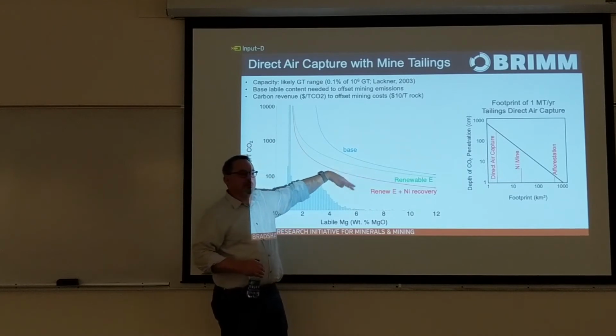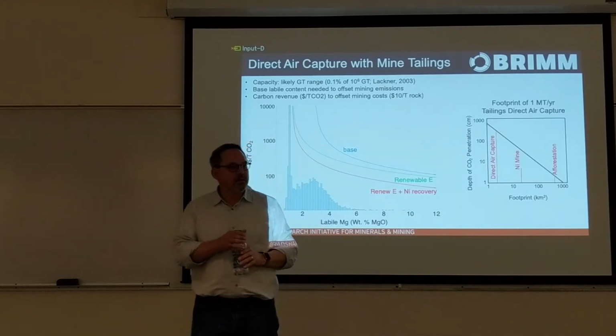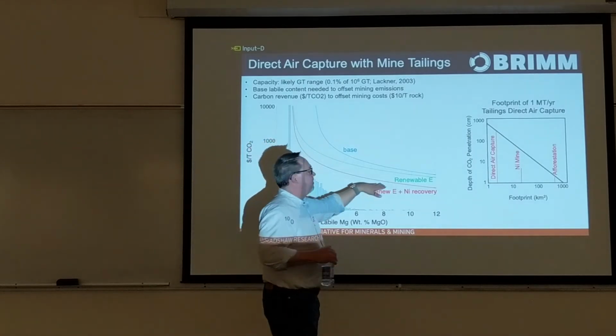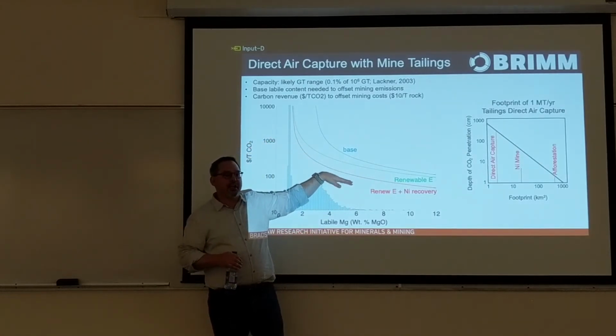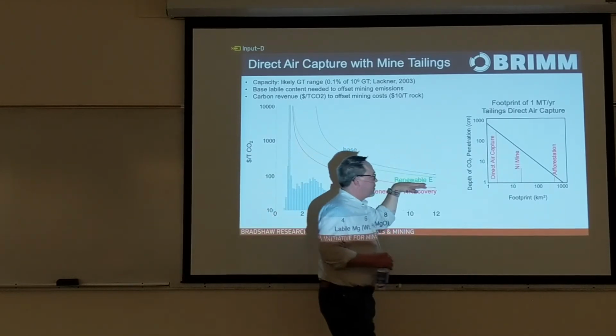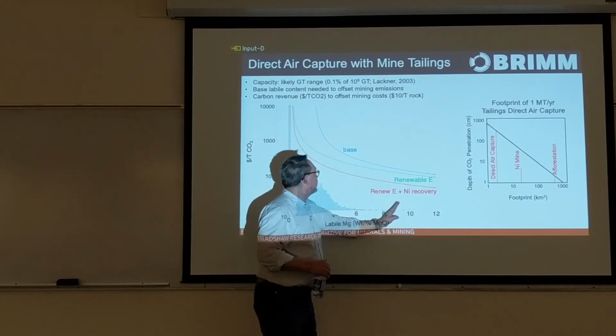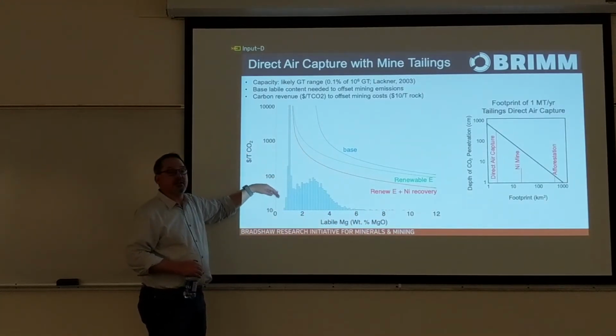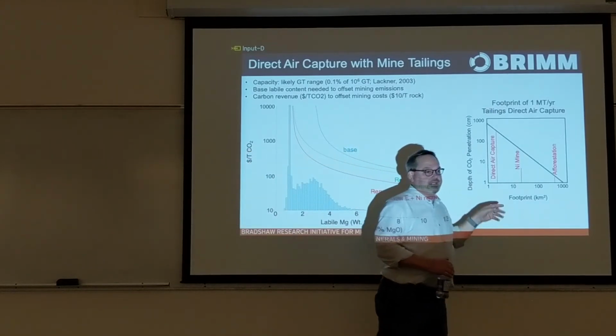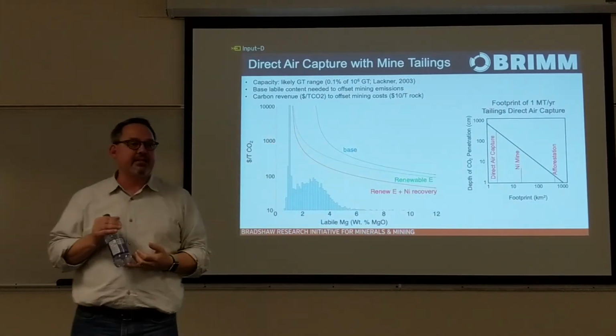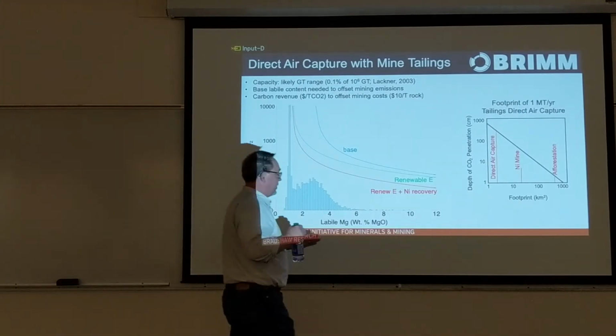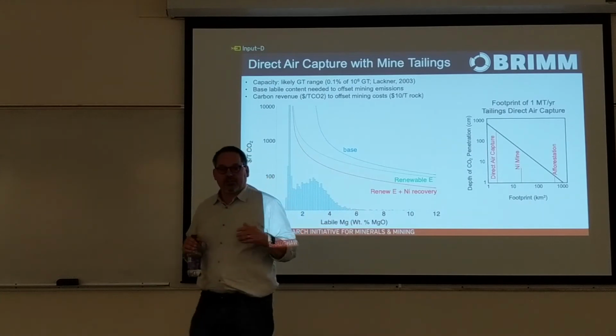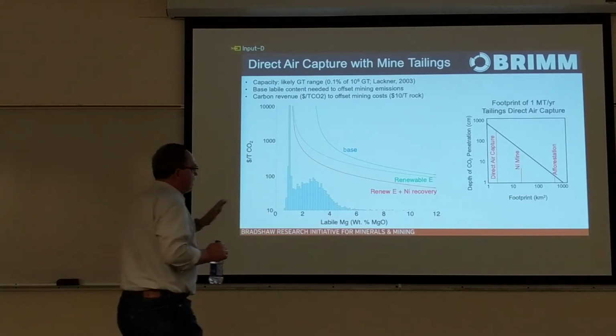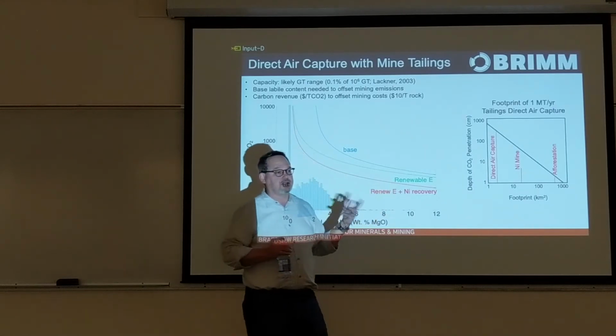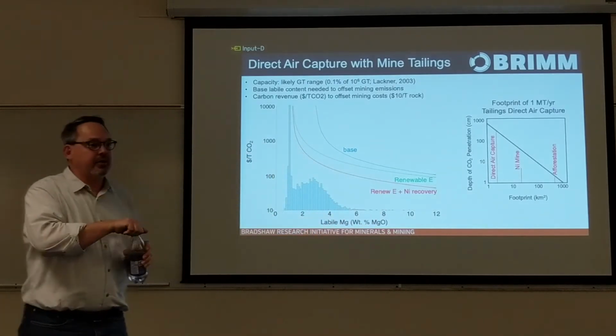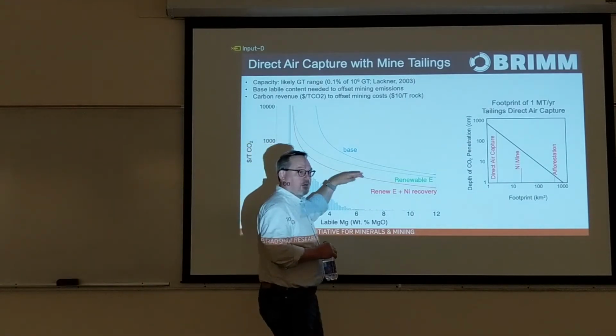If you further assume that you recover half of your mining cost by sub-economic commodity, in this case based on recovering $5 a ton of your mining cost from nickel, you're taking a sub-economic mineral deposit and topping it up with the carbon tax. You can see that out in this regime, we're now getting down into the tens of dollars per ton. So there potentially are places where you have large deposits, if they have this labile magnesium content, that are sub-economic, like Dumont is currently for nickel. A carbon tax of about $30 a ton might actually be enough to supplement the expense of mining such that you could run a mine at break even, and about half of your income would be derived from net negative carbon emissions.